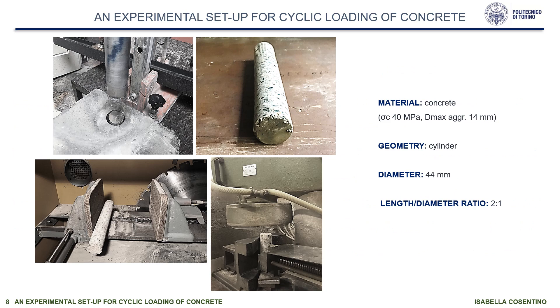To set up the cyclic loading process, cylindrical specimens of concrete were used. The specimens were extracted using a core drill from a hardened concrete block, then carefully examined and prepared by leveling, and subjected to compression testing using normalized procedures. This concrete was characterized by a compressive strength of about 40 MPa and a maximum aggregate diameter of 14 mm. A series of homothetic specimens with height-to-diameter ratio fixed at 2 were tested with a diameter of 44 mm, to ensure a ratio of 1 to 3 between the maximum size of aggregate and the specimen diameter, so as not to influence the measured resistance.